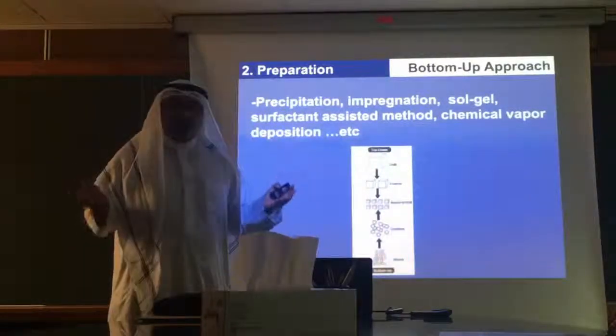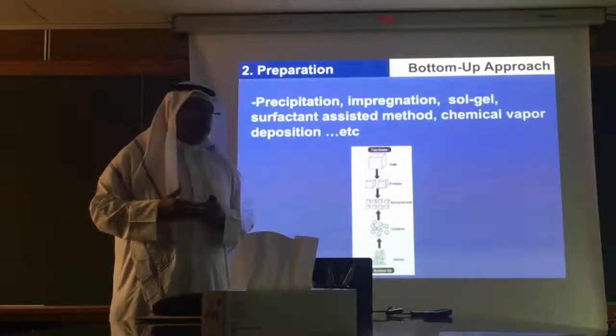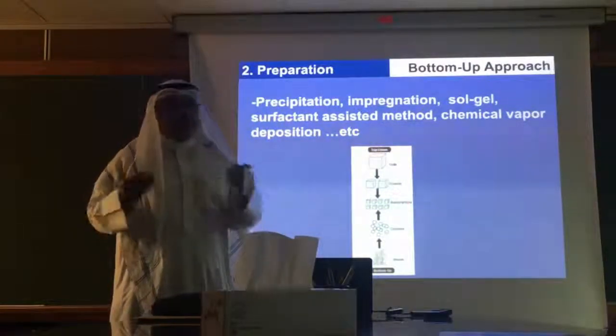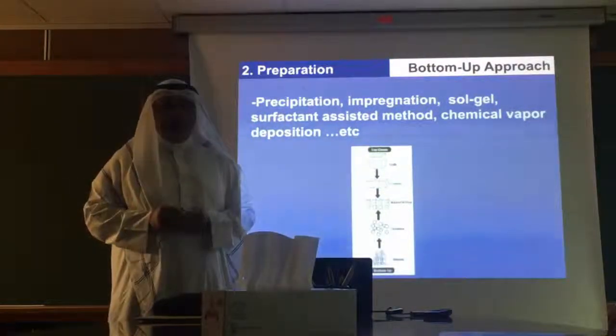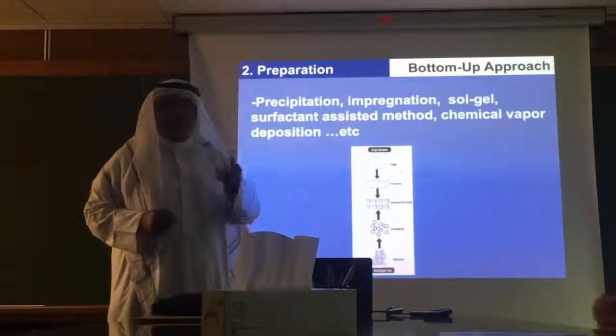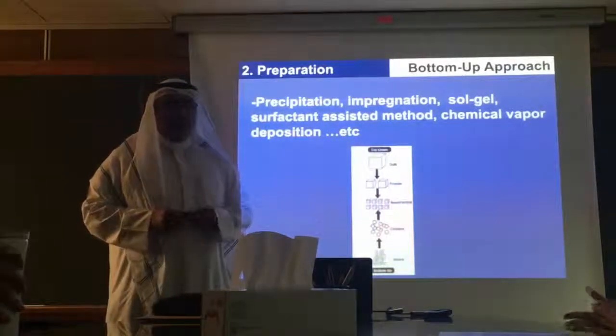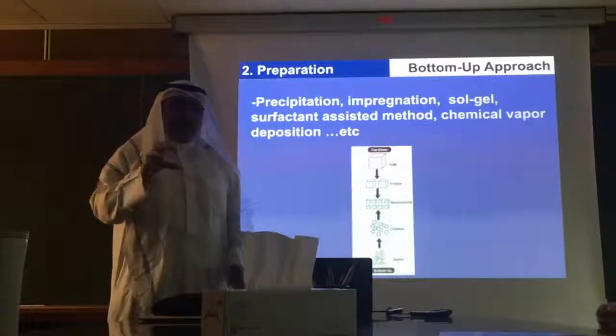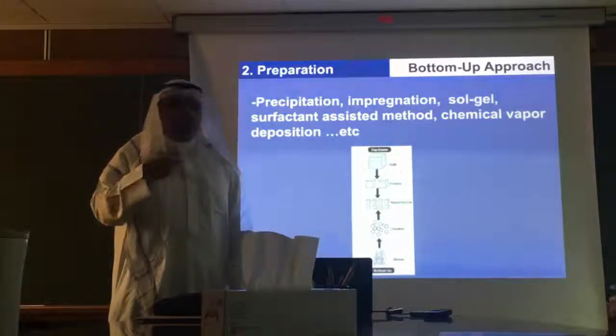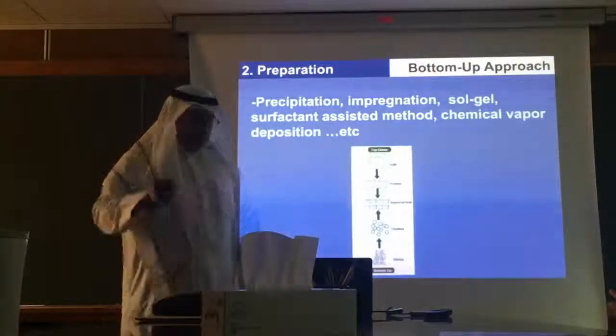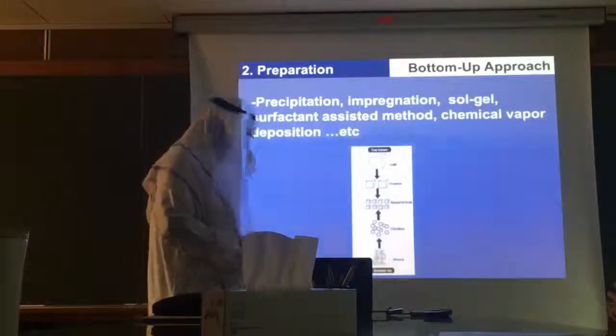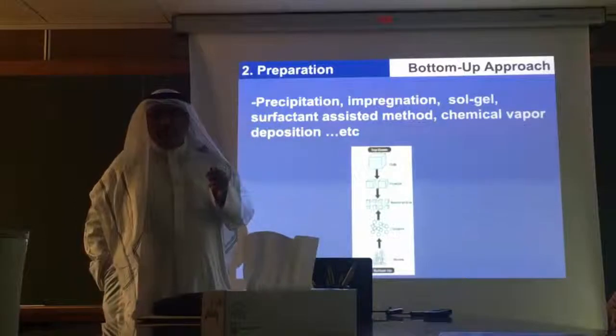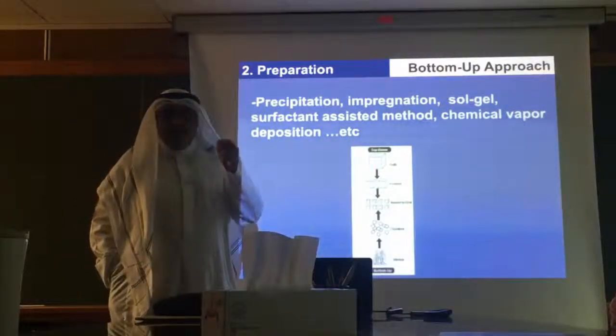If you want it as metal, you have to control the environment. You shouldn't expose it to air. If you want metal oxide, you can expose it to air, there is no problem. And sometimes we need to calcine it or heat it at high temperature, because sometimes the surface of the material is hydroxide, and I want it oxide, so I have to heat it to remove the water. Okay? And the bottom-up approach usually gets you monodispersed material.